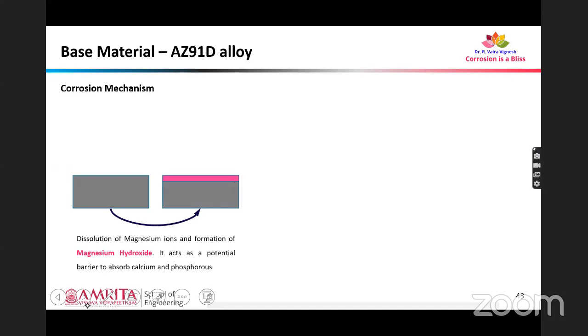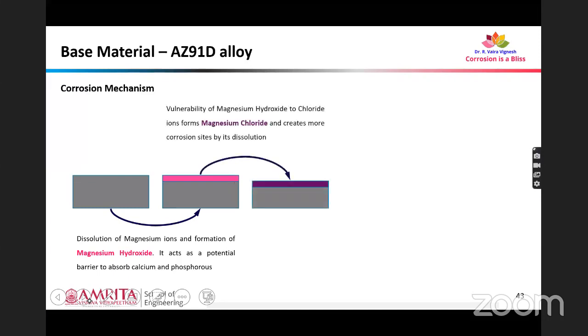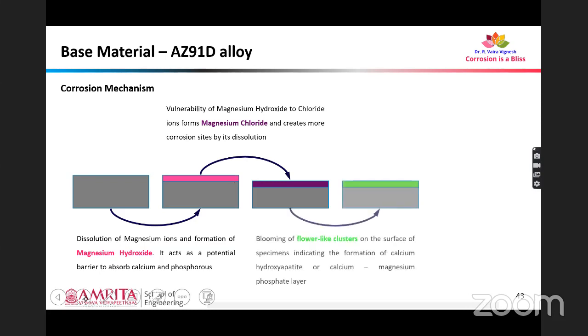Yeah, so the dissolution of magnesium ions and formation of magnesium hydroxide is the first step, and it will act as a potential barrier to absorb calcium and phosphorus initially. But then there will be formation of magnesium chloride that will create more corrosion sites by dissolution. And that will lead to the calcium and phosphorus present in the simulated body fluid interacting with magnesium to form salts or corrosion products based on calcium and phosphorus.